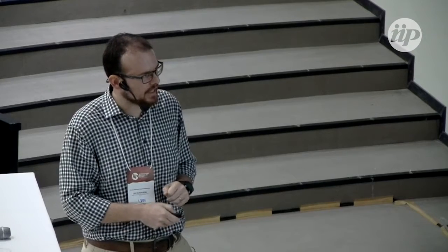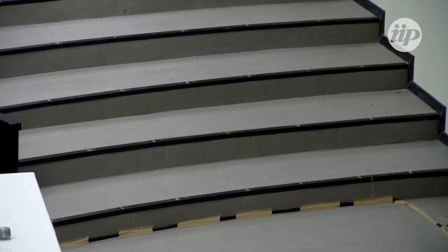What they did was a search of all possible structures with a certain number of carbon atoms in the unit cell, or in a supercell. They calculated the enthalpy per atom, and they number each structure with a given number. Graphene is down here, and what they see is that this structure is not very far from graphene. So in principle, the energy of this structure is such that it could maybe be synthesized in the lab. You just have to do your chemistry right.